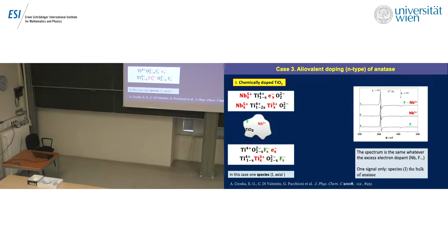Okay, alteration, third case, alteration of the valence with niobium or with fluorine, and it's very nice to see that the result is the same. There is no difference in the spectra of titanium dioxide containing fluorine or containing niobium or containing both of them. Always there is this first signal, so titanium 1 and not the other one.